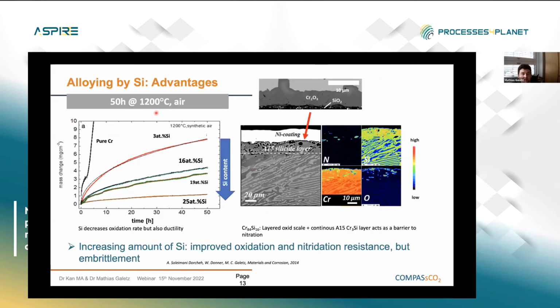Okay, next slide, please. So alloying silicon, as I said, has this huge advantage. As you can see here, pure chromium is basically not usable above around 900 degrees C due to strong nitridation and also strong spallation. There are high growth stresses in pure chromium. But when you add only 3% of silicon, we change to a parabolic behavior with much, much lower weight gain. And if you add silicon, all of a sudden we come into ranges that basically no commercial alloys can reach at the moment. At 1200 degrees, it's also a strength limit, of course, for nickel-based alloys. So this makes those systems very, very interesting.